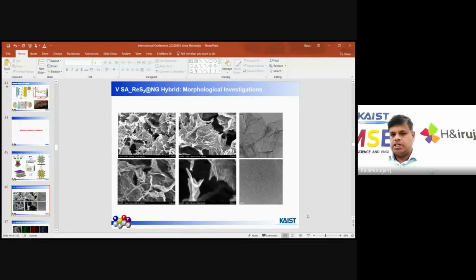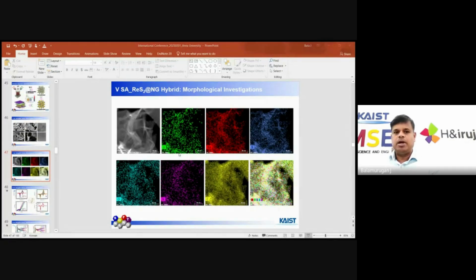And I show the homogeneous distribution of the elements. You can see perfect distribution of the rhenium sulfide and vanadium single atom. The vanadium single atom is at a lower density compared to the rhenium and sulfur, because rhenium and sulfur are homogeneously distributed over the graphitic carbon networks. You can see the carbon and nitrogen are also present because of the graphitic carbon, and the rhenium sulfur is homogeneously distributed, but vanadium acts as a single atom in our catalyst, our materials.